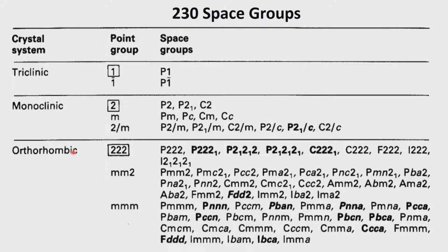Once we come to the case of orthorhombic symmetry, we have 3 point group symmetries, 222, mm2 and mmm. Now here you see that there are so many possibilities because we have different lattices which can come in. You see, in the case of the monoclinic system, we had a primitive lattice and a C-centered lattice, no other possibilities. In fact, we have not shown that, but maybe you can practice in one of the TA sessions; we can show that the C-centered lattice can also be I-centered and things like that. And if there is a B-centered lattice, it will go itself into a primitive lattice. This can be shown in a TA example.